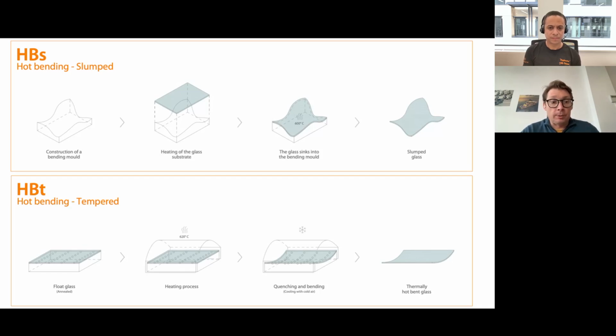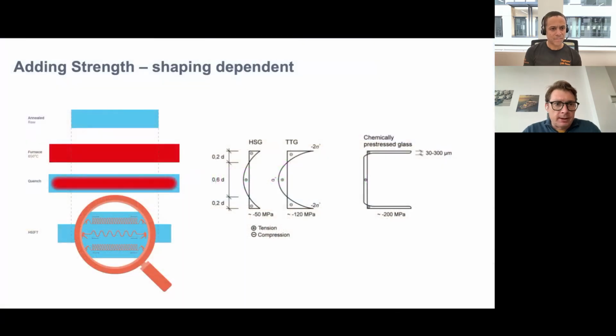We can also hot bend and temper. So this is the same process as the flat tempering furnace, but as it comes out of the furnace at 600 degrees, and as it goes into the air quench, rollers bring up the edges so it can be curved before it's finally cooled. But increasing strength. So when we're increasing strength, what are we doing?